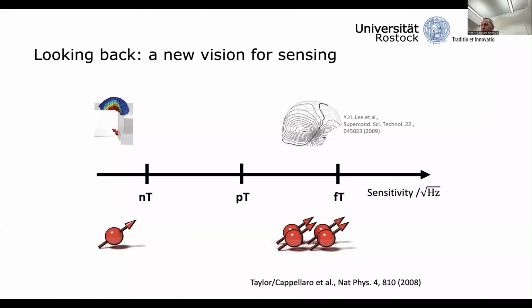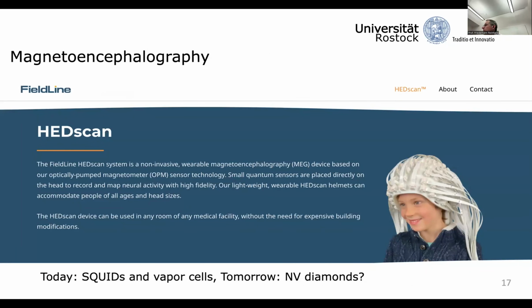Now, I would like to draw your attention to one thing. In the theory proposals that in a way started this field roughly 15 years ago, this was not the only vision that was put forward. So clearly, using a single NV to do NMR spectroscopy was already part of the first theory proposals. However, there was on fairly equal footing a second vision that by integrating NV centers into large ensembles using densely doped diamonds, we would be able to achieve sensitivities that would be competitive with essentially superconducting magnetic field sensors, as those that are being used for magnetoencephalography. And if that would be possible, that would be another very exciting direction for applications, because, for example, it would be a competitive, cheaper room temperature alternative to do magnetoencephalography.